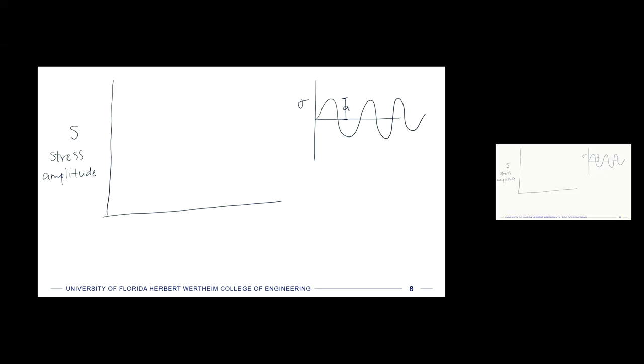And so that stress amplitude, if we plot that, this would be like in time. But if we plot this according to cycles, then lots and lots of experiments show that there's a high region and it decreases like this. And there's a lot of uncertainty in this, right? It's not a perfect line. And then eventually it sort of plateaus off, right? Something like that. And we call this flat region the endurance limit. Right? And if you have stresses that go below that, you don't really have to care about fatigue because you are expecting the material to have very long endurance. Okay? So that's the endurance limit.